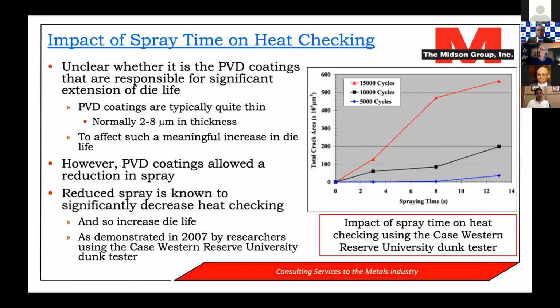However, we do know that reduced spray can significantly affect heat checking. And it's the application of the PVD coating to the die that allowed a significant reduction in die spray. So here's some data on the right-hand side of this figure. This is data taken from research results from a university in America called Case Western Reserve University. They have what they call a dunk tester. And the dunk tester